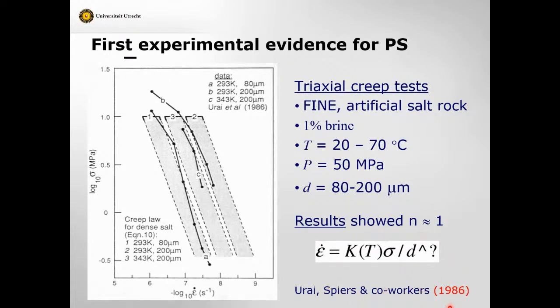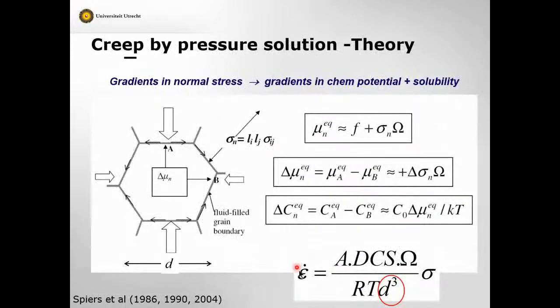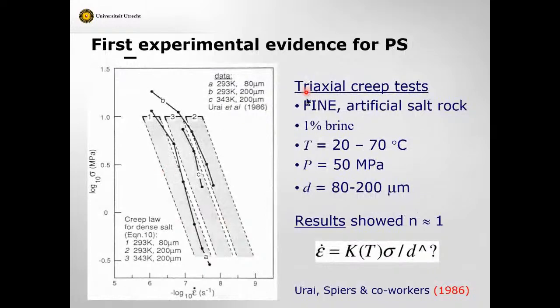This mechanism should operate. Now, the very first experimental evidence we found for this was really many years ago. It's only 35 years ago. 1986, Janos Urai and I did experiments on fine-grained salt. Why did we do that? We did that because, look, our theory predicted a very strong dependence on the grain size. So natural salt crystals are huge. Natural rock salt has very coarse crystals. This will be slow. But what could we do then to see it? We made fine artificial salt with a very fine grain size, and we did creep tests.